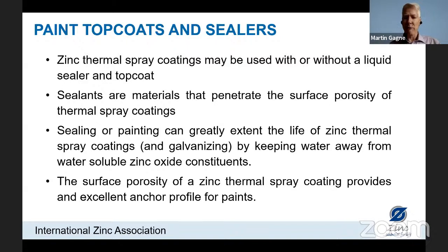We saw an example where if we have paint on steel and we scratch through, the iron will begin to rust. And iron corrosion products can take up 7 times the volume of the iron. So this puts enormous pressure on the paint film. So at those edges, it can't withstand that pressure. It starts to peel up, and we get a phenomena called underfilm creep corrosion.